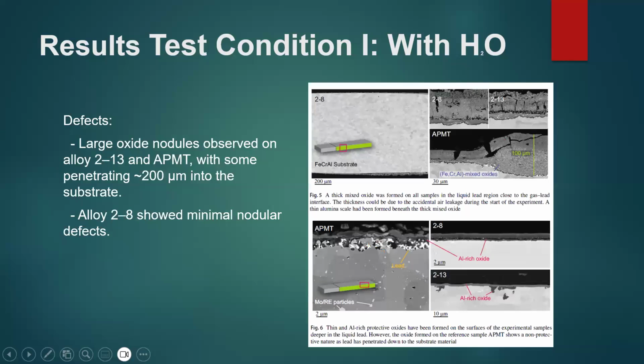We can see defects like large oxide nodules observed on alloy 2-13 and APMT, with some penetrating around 200 micrometers into the substrate, while alloy 2-8 showed minimal nodular defects. In this figure, this shows nodular defects, and this shows a large oxide nodule.